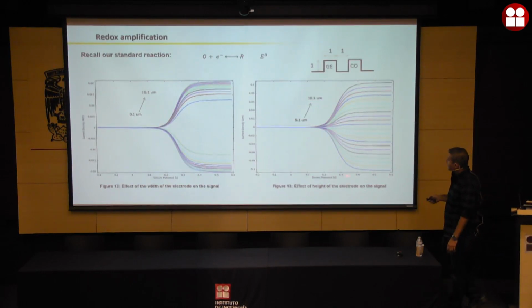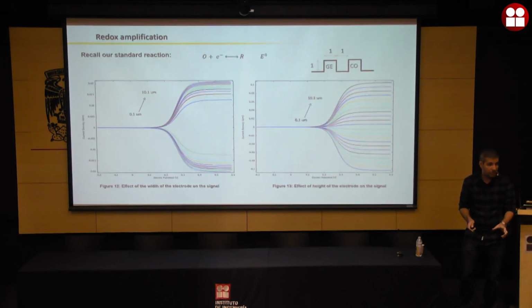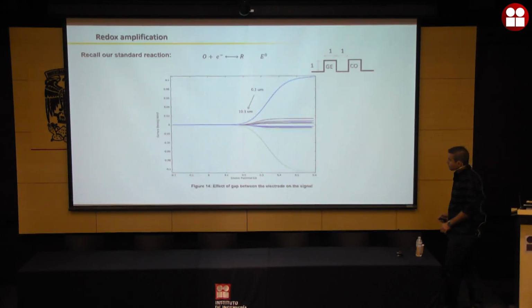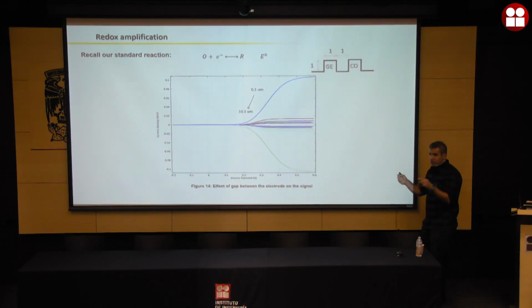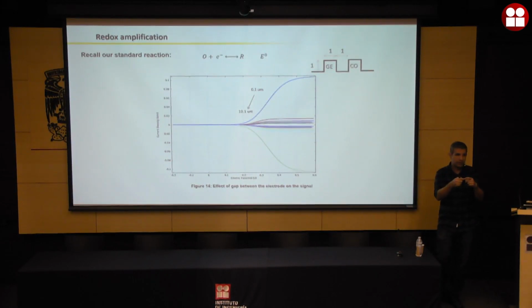And if I change the height of the electrode, because I'm basically having more of those redox cycling happening between the electrodes, I'm also amplifying the signal, right? So as I increase the height, the current amplifies. But the interesting part is here. If I bring these electrodes as close as possible to each other, I can see almost a 50-fold amplification of the signal. So the point is to bring these electrodes into each other's diffusion layer.